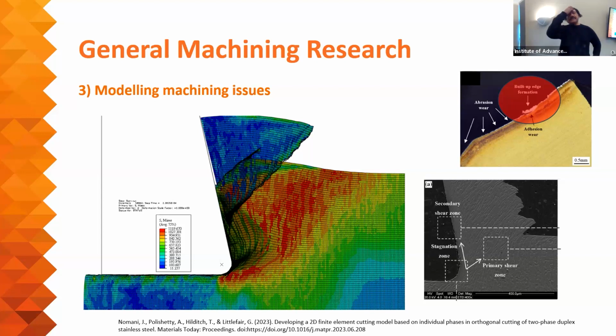Okay. So those were basically what I considered 3 levels of machining. First one, machinability studies, which is happening at the very surface, where you have input variables, which is parameters, and you get output variables, which is performance. But that level is good for publishing. Also helps identify machining issues. And that leads into the second level, which is characterizing machining issues. So find what are the causes of these, or what are the fundamental triggers which cause these issues. And then level 3, to try and model and replicate what you see physically.